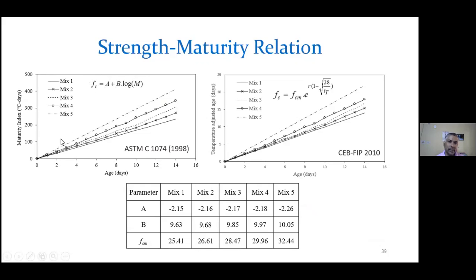As per this code, we find out the value of log M, right? So maturities are known to us, and if you use that, we can find out the values of A and B by this age-maturity index curve. And this is for CEB-FIP, that is temperature T versus H, and we find out the f_cm because R is already known to us for a particular mix. So the code gives you the value of R. So what are the constants A, B, and f_cm? A, B, and f_cm are noted here in this table for 5 different mixes.